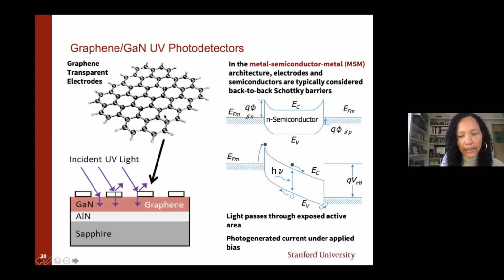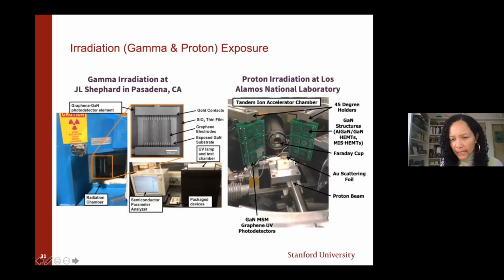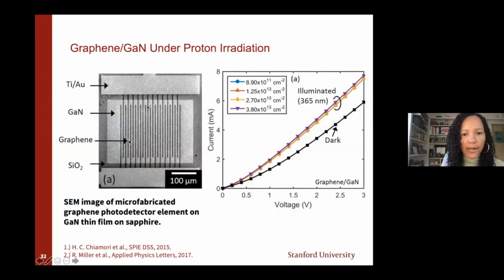It's also transparent. And so we've created this ultraviolet photodetector from gallium nitride using graphene as the conductor. So these interdigitated electrodes. We've irradiated in proton environment, high energy protons at Los Alamos National Lab. These are, again, little samples here, each student has these samples that we put on. And then this is the graphene on GaN photodetector. So these are interdigitated electrodes.